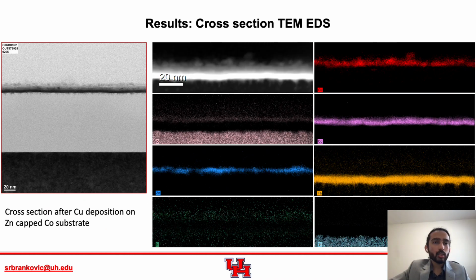This slide shows a cross-section TEM EDS analysis for the substrate after copper deposition. And we can notice that there is a continuous copper layer after deposition on top of cobalt. And the cobalt layer is completely intact and there is no corrosion of the cobalt layer observed. And then tantalum and silicon layer and so on the wafer substrate. So this proves the point that we are able to deposit copper by replacement of zinc while keeping the cobalt layer intact underneath.